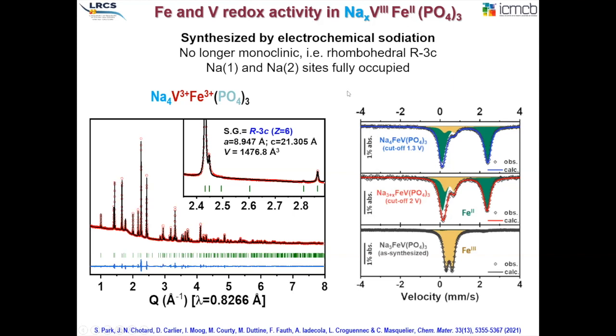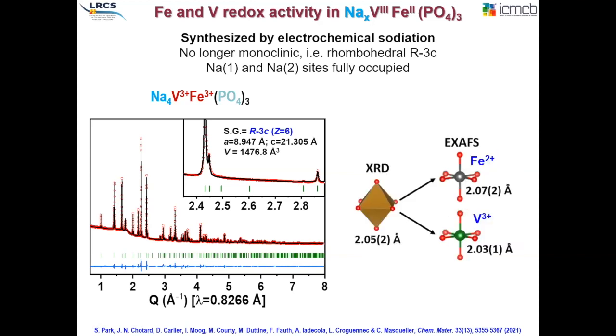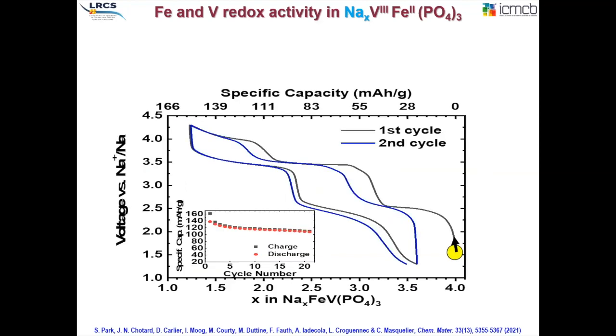So we have a compound, Na4 FeV, that is obtained electrochemically and chemically by sodiation, by chemical sodiation. And we were able to indeed determine that the environment around iron and the environment around vanadium looked very similar from the X-ray point of view, but we were able to separate the respective contributions from EXAFS and determine that indeed we had iron 2+ and vanadium 3+ in the same cathode. The electrochemistry is pretty fascinating.